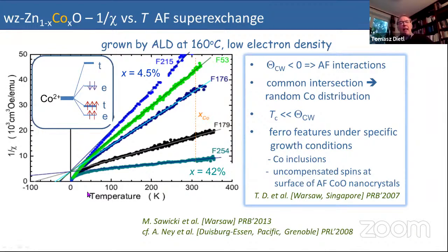And if you think a while about the Curie-Weiss temperature, the Curie constant should be proportional to magnetic ion concentration. In a random system, the Curie-Weiss temperature is also proportional, in high temperature expansion, to ion concentration. So at 0 temperature, this x dependence cancels. And actually this crossing of these lines in one point demonstrates very beautifully that we have random distribution. If you would have correlated distribution, we would not observe such crossing. So we have random distribution.